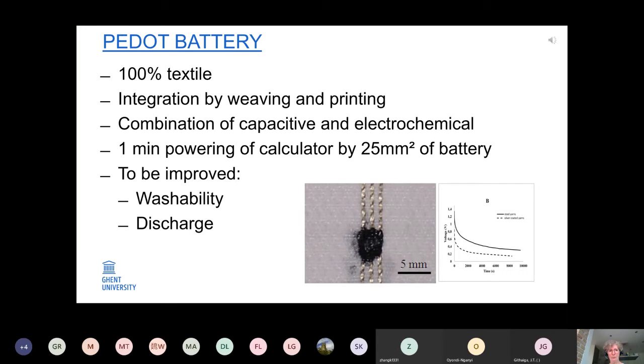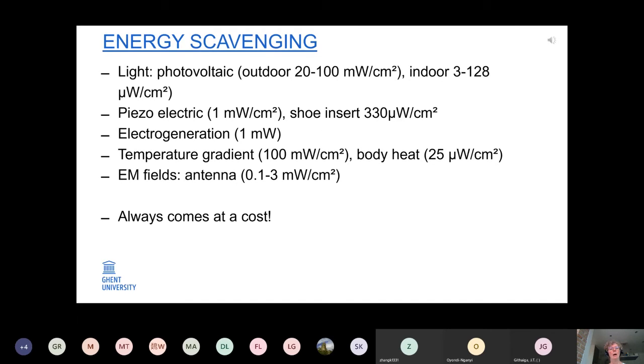Here is an overview for energy scavenging of different principles and just some indicative values of power that can be reached. Photovoltaic for sure is one of the better materials in terms of output power. Outdoor, we can reach 20 to 100 milliwatts per square centimeter. Indoor, this is around 1,000 times less. Piezoelectric shoe inserts, for instance, have a reported power output of 330 microwatts per square centimeter. Electrogeneration, 1 milliwatt. It's difficult to express this per unit square.